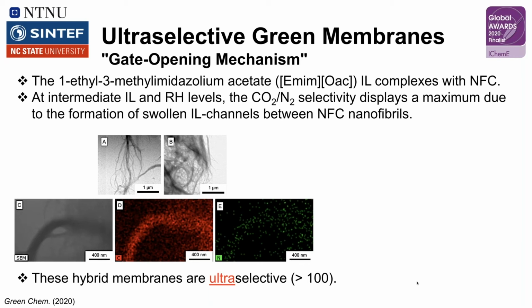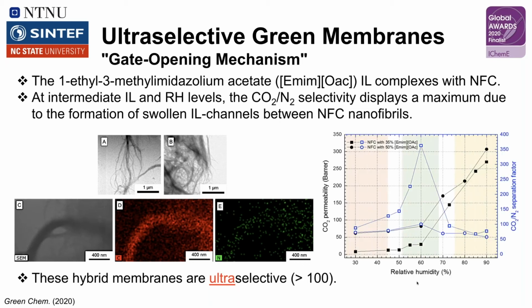Well, once we start putting in the ionic liquid and introducing relative humidity, we find something that's very, very interesting. And that is that when we look at the permeability of CO2, we find that as we add in both moisture and ionic liquid, we see increases in the permeability. Not initially though, but at some point, we see a break here where all of a sudden the permeability starts to shoot up. And we're talking about permeabilities going from about 100 Barrer or less to now about 300 Barrer. But that's not the exciting point. The exciting point is looking at the separation factor.